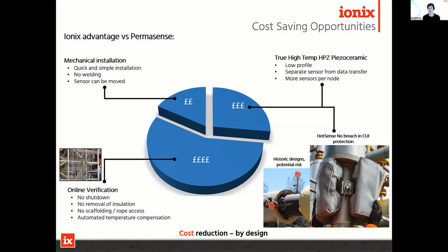So our probe is a true low profile under-insulation system. It doesn't breach or break through the weatherproofing or the insulation. It means that you can reinstall this over the probe and give you the kind of integrity that you need for your CUI defenses, preventing water getting in. It also means that the probes aren't exposed to damage, people bending them, or wind blowing on them, causing vibration and fatigue, for example.